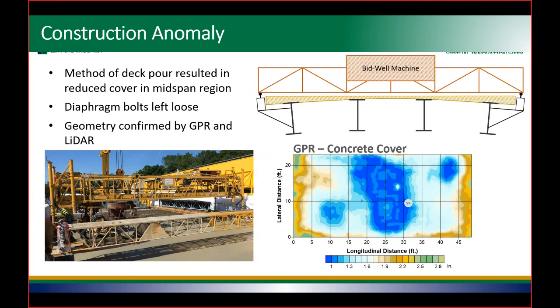When the construction was finished, actually several months after, we realized there was a significant error during construction, and it turned out to be a result of the Bidwell machine that was used to pour the deck. The Bidwell machine ran along rails that were mounted to the exterior girders. Due to the configuration of that structure, the weight of the Bidwell machine caused those exterior girders to rotate, and the bolts on the diaphragms were left loose, further allowing rotation of those exterior girders. In the process, the rails deflected downwards as a result of that rotation, and we ended up having about 3/4 inch less cover in the midspan region. So instead of 2 inches of cover, we only got an inch and a quarter in that midspan region.